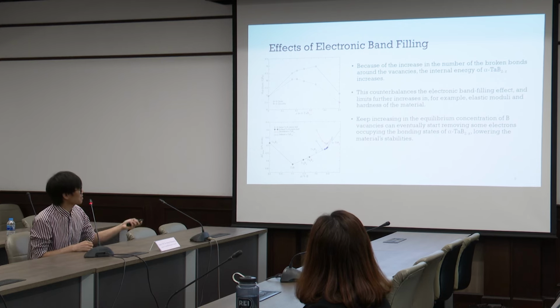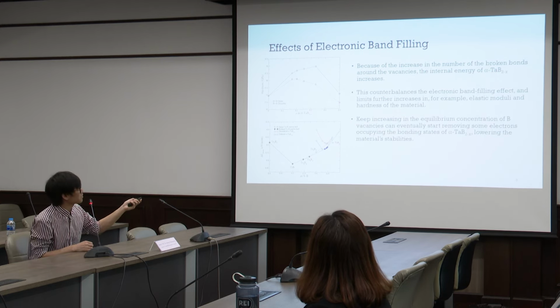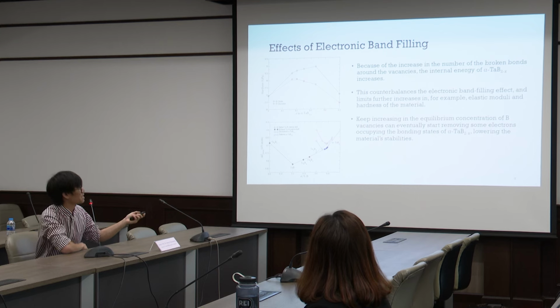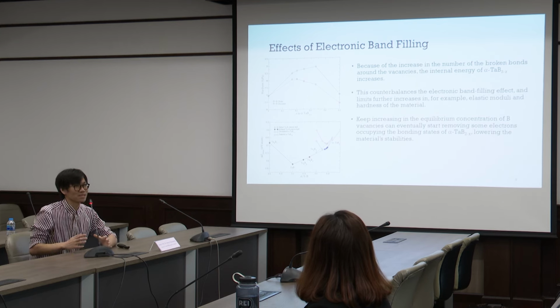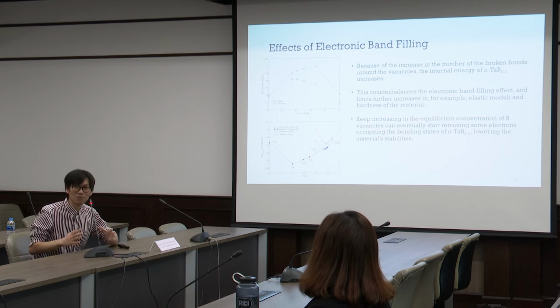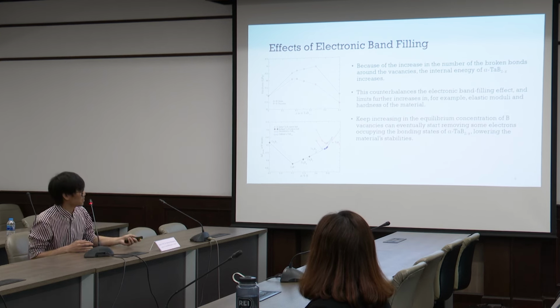And if you further increase the concentration of boron vacancy, at some point some electrons in the bonding states will be removed from the electronic states, and that will drastically decrease the stability of the material TaB2.